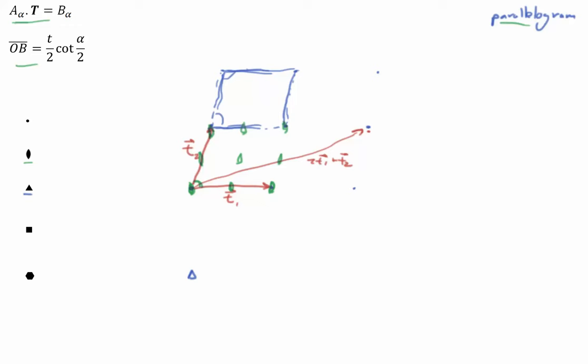We've already seen that if I have a single translation vector here, then this original rotation axis, let's call it A sub alpha, will bring this new rotation axis and rotate it by 2 pi over 3 radians up here, and I can have another translation vector. They will repeat, and in addition, I have new rotation axes that occur inside the unit cell.